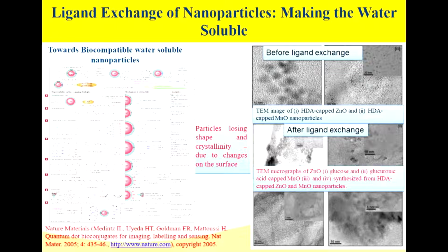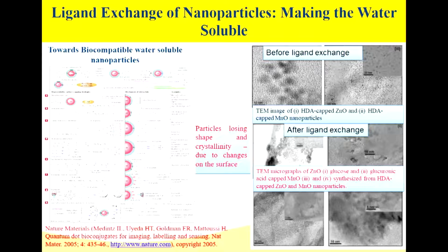These are a range of biocompatible molecules that you can find that can be very useful, depending on where you're going to target the use in the body of a human being or any animal. Although this was successful, it also comes with its own challenge. Once you do what you call ligand exchange, where you swap the ligand that you started with, which is not soluble, for the soluble ones, you end up with particles that are not as big as they originally were, or perhaps even agglomerated, like in this case here. But here you can also end up with some very nice discrete particles that are very small, and finally you can see that they become even smaller and smaller.